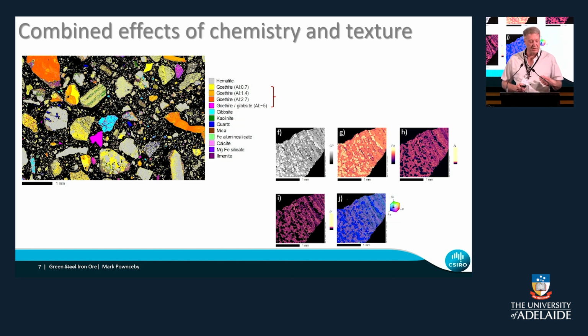But when you start to look at other impurities like aluminium, which is in H, you can see that aluminium almost is exclusively in the goethite. Doesn't really report to the hematite. Phosphorus is in I, and so phosphorus is a key problem in Australian iron ores, and it also occurs primarily with the goethite. And you can notice that there's a correlation between phosphorus and aluminium.